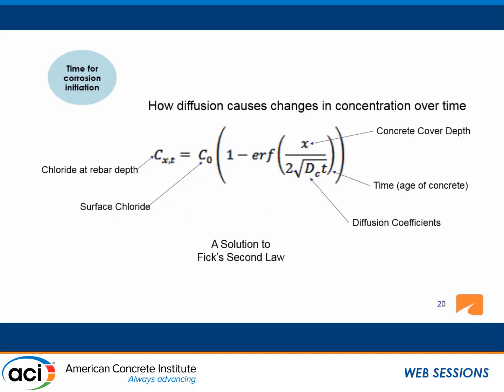So we are only going to look at the first phase, the time for corrosion initiation. This has been successfully, quite reliably modeled using Fick's second law of diffusion. And there are other methods as well. This method is what we chose, and we used a fully probabilistic model developed at Virginia Tech.